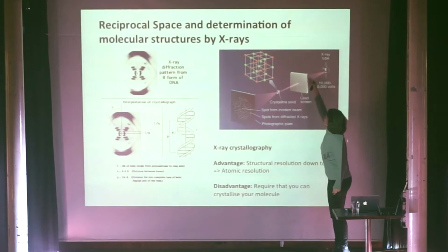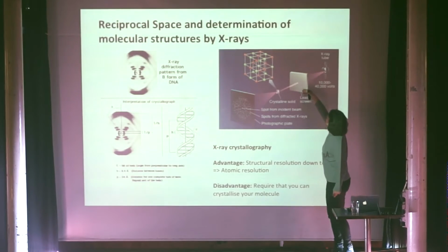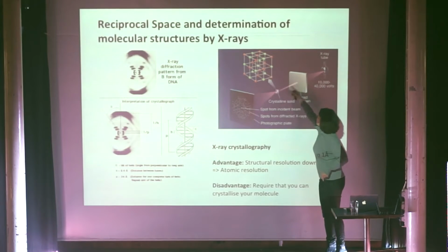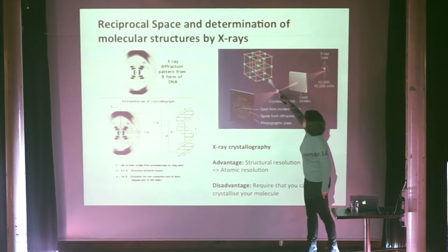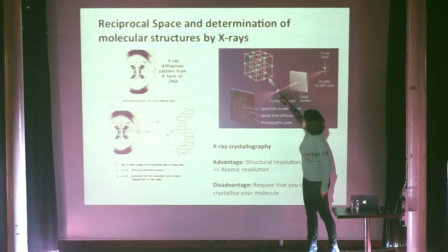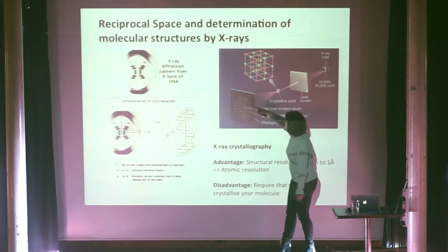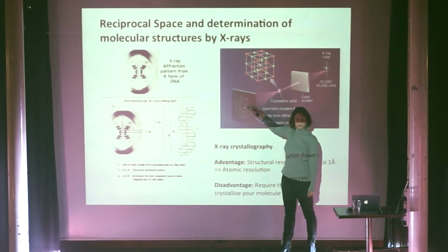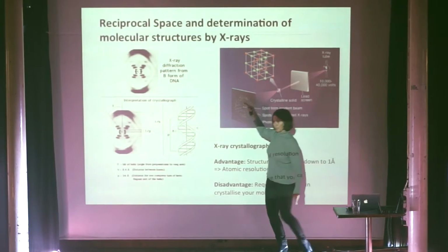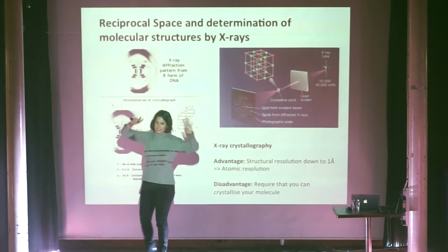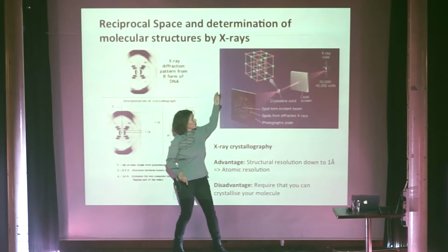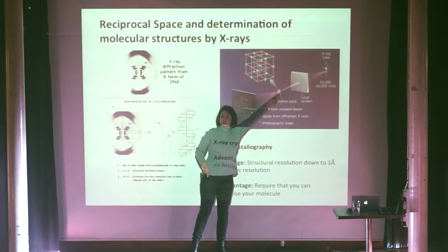And then if you place, here's a lead screen that is placed after the X-ray tube, where you drill a tiny hole in it so that you get a very well-focused X-ray beam out. Then the X-ray beam comes out, it interacts with the crystal structure here, and then you get this nice diffraction pattern out. And here we are in reciprocal space, so you can see this is really, really beautiful. Nice spots, and they sit in a symmetric pattern. And from this beautiful symmetric pattern here, you can calculate backwards and find out what the crystal looks like.